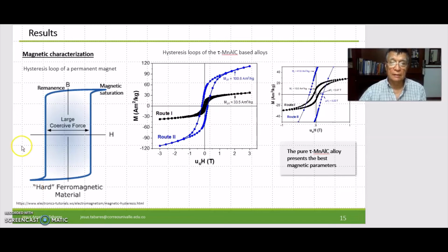Here I present the hysteresis loops obtained for the two types of tau manganese aluminum based alloys for route 1 and route 2. We clearly see how the relevant magnetic parameters of the pure manganese aluminum alloy, the tau phase, are better than the ones of the solid heterogeneous mixture with 91% of the tau manganese aluminum carbon phase.